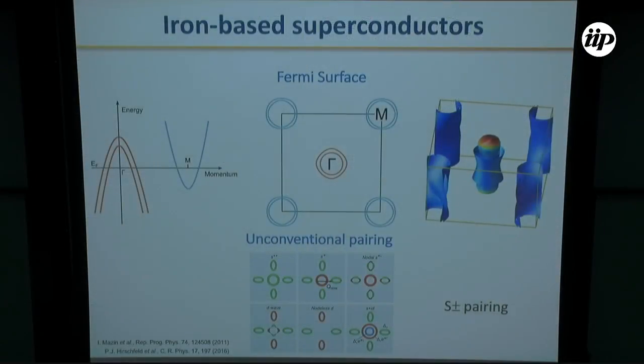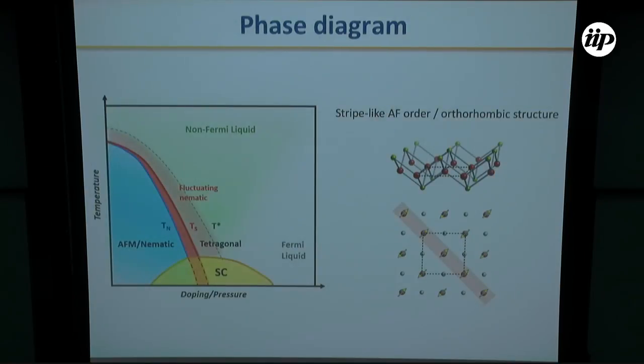So different pairing symmetries have been discussed in these materials. Most of them involve the change of the sign of the superconducting gap over the Fermi surface. And today there is some consensus that in most of these materials, superconductivity is consistent with S plus minus pairing, which means that we have an open energy gap over the whole Fermi surface, but still it changes sign in different parts of the Fermi surface.